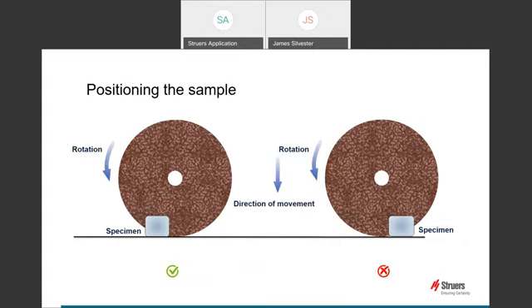If we take a look at the positioning of your sample during cutting, ideally the sample to be cut will be clamped just in front of the center line of the cutting wheel movement. This ensures all the cutting force pushes the blade in the same direction on the downward part of the wheel rotation. If this is not the case, due to clamping position or component geometry preventing cutting in this sort of position, special care must be taken as the wheel will be pushing and pulling away from a component at the same time, which can cause vibration and movement of the component within the clamp. This is especially noticeable on some large or deep cuts.